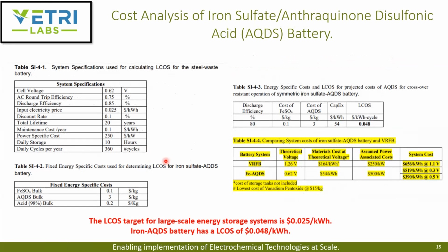So the overall point of this paper was to meet this LCOS target. The LCOS target for the large scale energy storage system is actually, this is wrong, it's 2.5 cents per kilowatt hour. And theirs is only about 4 cents per kilowatt hour. To calculate this LCOS, they used system specifications, right? The overall cell voltage, we know it's 0.62, and you assume a daily storage of 10 hours. Daily cycles per year is about 360 cycles. And there is a fixed cost, right? FeSO4 is only 10 cents per kilogram and AQDS is $3 per kilogram. By considering this and only 80% efficiency, they obtained only about 5 cents per kilowatt hour when you use the AQDS battery.